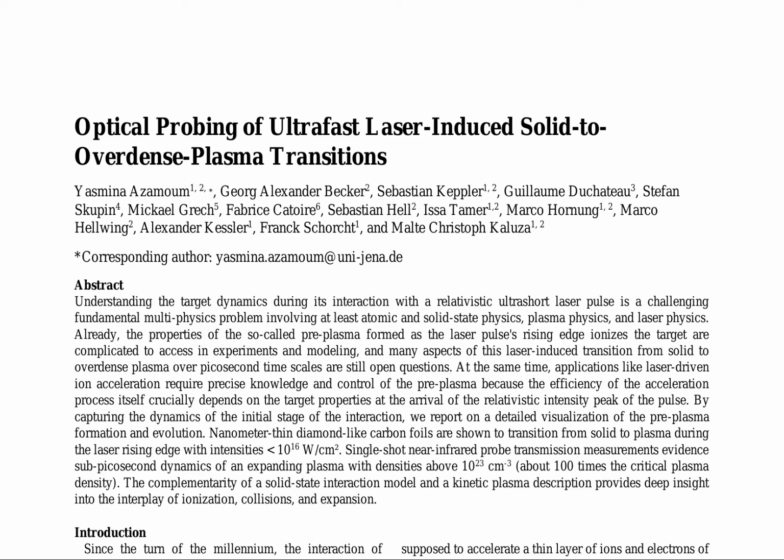Using nanometer-thin diamond-like carbon foils, the authors demonstrate the transition from solid to plasma during the laser rising edge with intensities below 10^16 W/cm². Single-shot near-infrared probe transmission measurements reveal sub-picosecond dynamics of an expanding plasma with densities above 10^23 cm^-3. The authors highlight the importance of precise knowledge and control of the preplasma, as it crucially affects the efficiency of laser-driven ion acceleration.